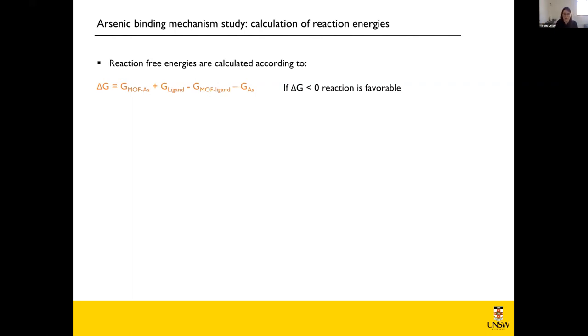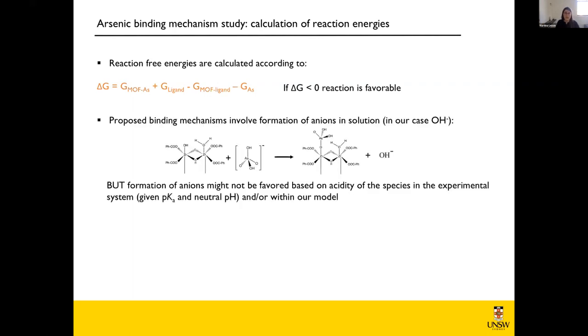The other big question about modeling this reaction that I want to quickly bring up is that we're displacing a ligand, and this ligand is an anion. So we're releasing an anion, and depending on the pH conditions and also depending on our model, releasing an anion might be making this reaction artificially unfavorable. Especially given the pKa of water, which is 15, you can probably guess that it would be much better if we could protonate this hydroxide and produce a water molecule instead. And so this is exactly what we did.